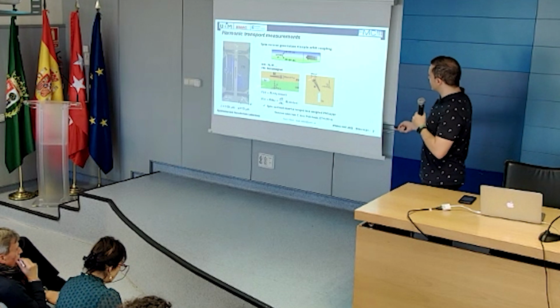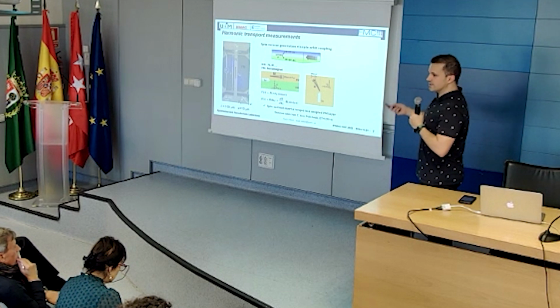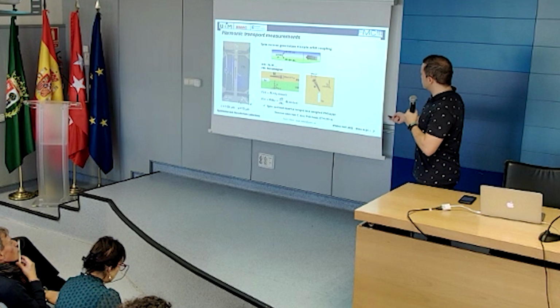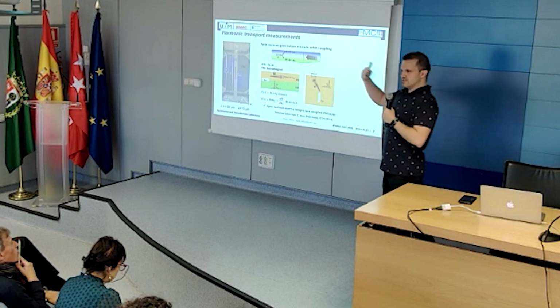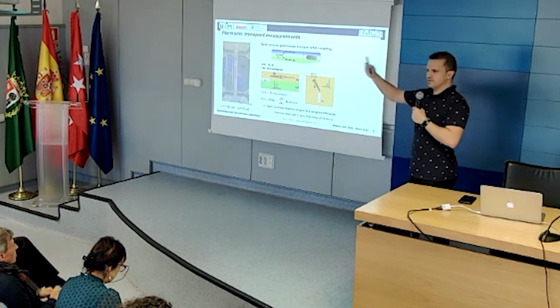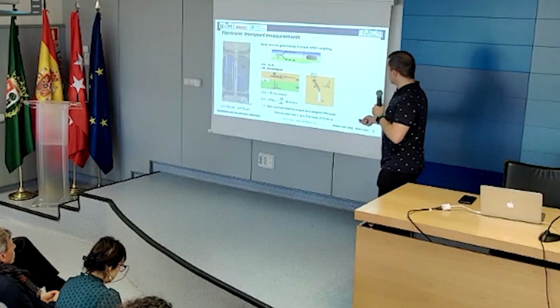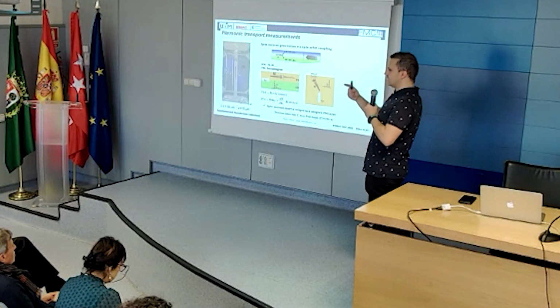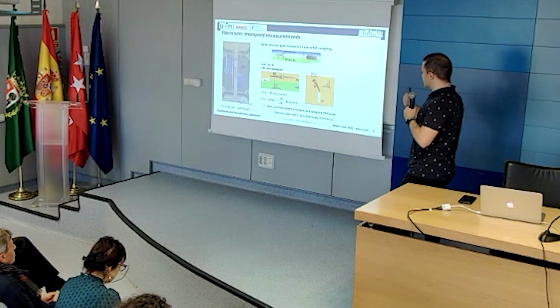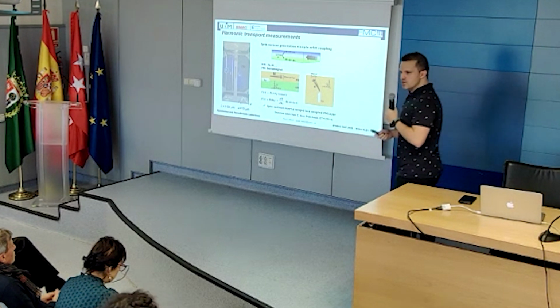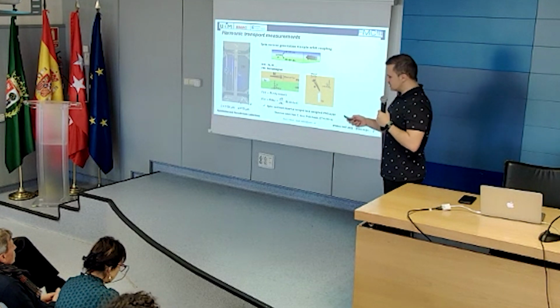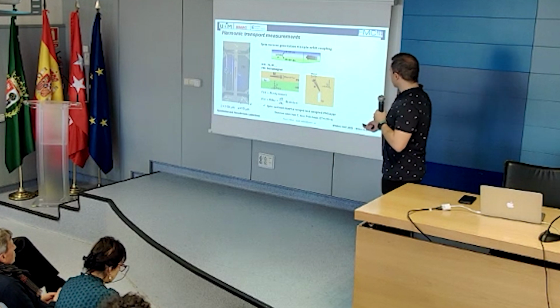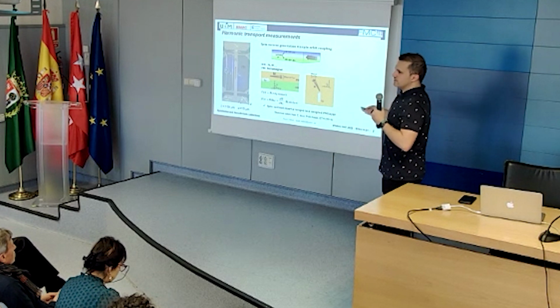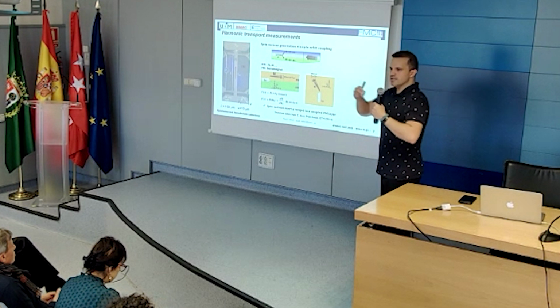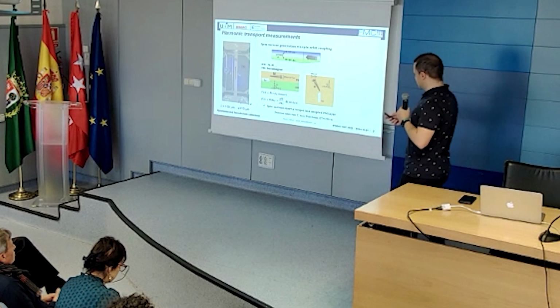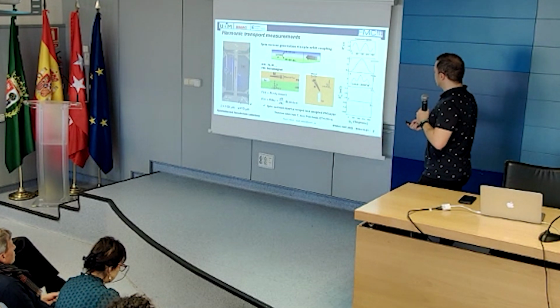You see this in harmonic transport measurements. Basically, these oscillations of the magnetization are what you pick up as the second harmonic. They give you an additional non-linear electrical resistance, and that's what you pick up in the second harmonic. In the first harmonic, you pick up whatever standard measurement you would do with a DC measurement. Essentially, that's what you are more used to.